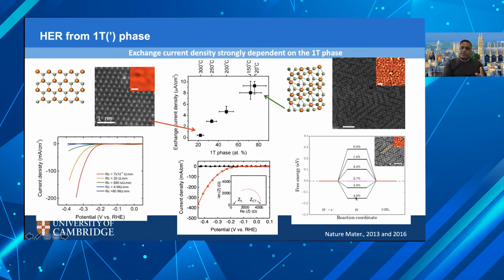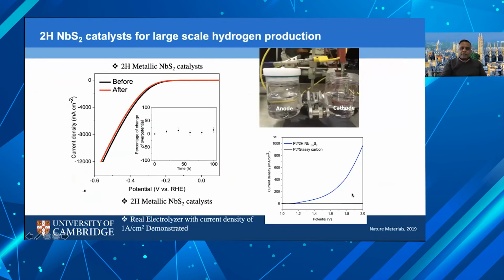We've also done theoretical calculations to show that in addition to the metallic phase and the thermodynamics, there's also strain when you do the phase conversion, and strain plays a critical role in driving the HER reaction. That's shown by this free energy diagram.